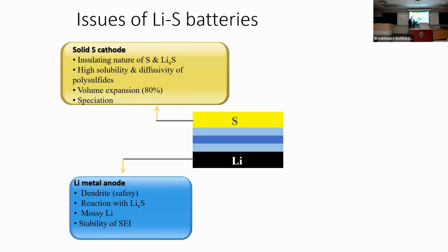It dissolves, reforms. And for that interface stability, of course, there are many techniques studied, not only by microscopy, there are in situ microscopy and spectroscopy as well, but also by studying it by impedance spectroscopy, where you can really monitor the impedance of this layer, a thin layer, whose capacitance therefore becomes very, very high. Yeah, because it's a very thin layer.